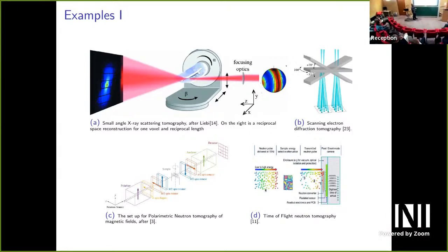Over here in Cambridge, they're doing something similar with electron diffraction tomography. So mathematically, that's quite similar to X-rays. Physically, it's on a very different scale. An idea, for example, is to take crystalline material like silicon, such as you make a chip out of. It would have a diffraction pattern with lots of spots, and with strain going through the path, the spots get blurry, and you try and deduce the strain.